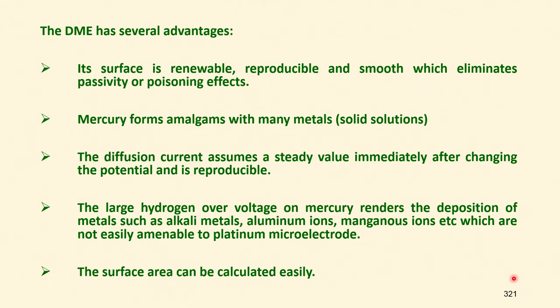And diffusion assumes steady value immediately after I change the voltage. A large hydrogen overvoltage on mercury renders the deposition of metals such as alkali, aluminium and manganese possible. They are not amenable for polarography with a platinum microelectrode, where surface area can be calculated very easily. Five advantages. All the five are really good,